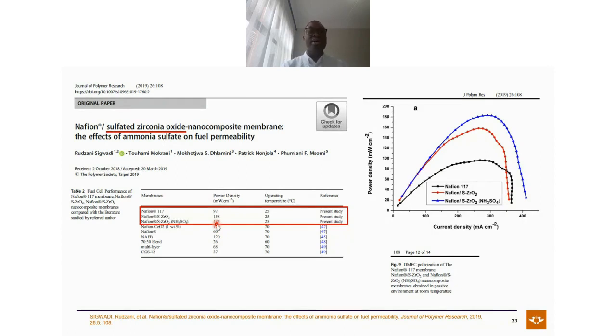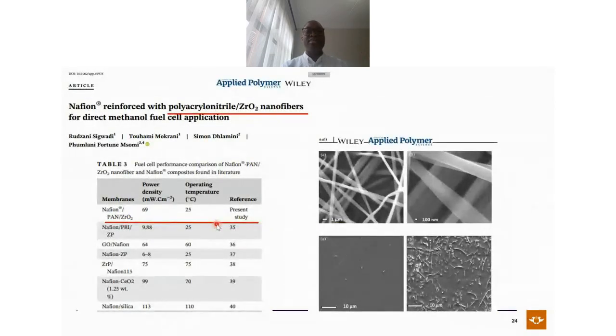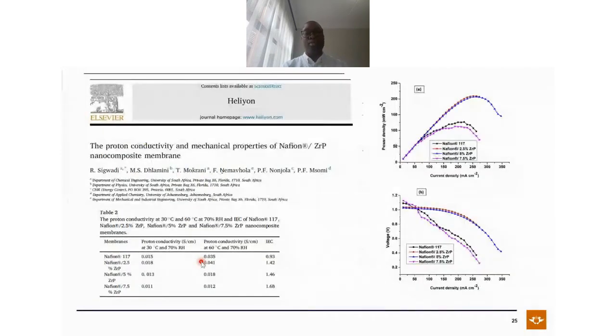Well, we went a step ahead. We looked at Nafion and said, let's add zirconia oxide based nanofibers. You know, nanofibers have high conductivity and can also have a higher transport system. As you can see, this is also a study that we've made. We had a power output of about 69, which was also one of the better outputs when you have Nafion alone. So we're saying nanomaterial works. We also looked at the proton conductivity of Nafion, but in this case we have zirconium and we added phosphoric acid, so we phosphonated it. When you look at the conductivity of Nafion alone, this is Nafion 117, it was about 0.07, but the moment you add different types of zirconium phosphate, you have an increase. This is the output of the material.